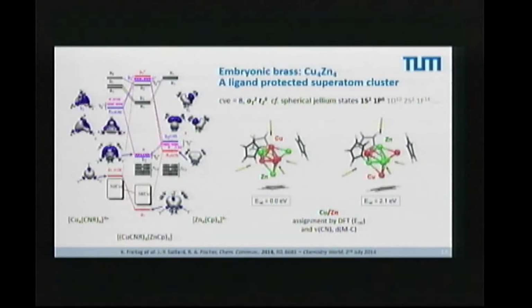Now, I can stress in the discussion a little bit what the ligands are doing. Now look at this case of copper 4, zinc 4. It's a nice tetrahedron embedded in a tetrahedron. So let's look first at the left one. So the red atoms would be copper here and the green atoms would be zinc. You can recognize a tetrahedron here, but all the green ones also form a tetrahedron. So each of the zinc would bridge threefold a face of the tetrahedron. Now in this particular case, we calculated that and we crystallized it. The Cp* organic ligand is bonding to the zinc, and this kind of an isonitrile ligand is bonding to the copper. And this is the outcome of the X-ray crystallographic analysis matching with the NMR and the IR, where you can assign the binding of the ligands to the different metals.